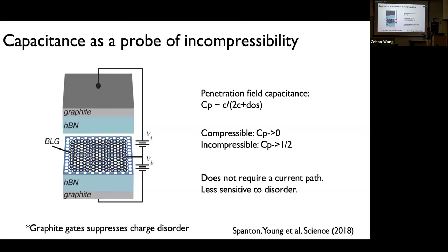One advantage of this, compared to the transport experiment, is that it doesn't require a complete current path from, say, electrode A to electrode B, and it's also less sensitive to disorder. You can make a qualitative statement, for example, if you see a spike in this penetration field capacitance, it means that you already have an incompressible state. And then you can use the method I described to look at the evolution and analyze those trajectories, and already you will be able to make a claim.